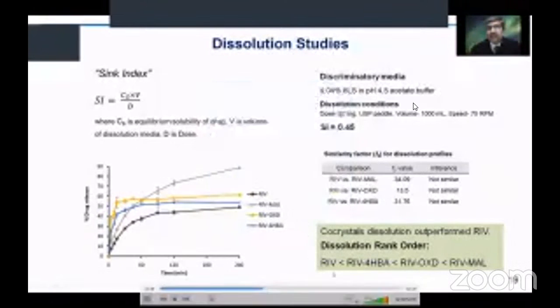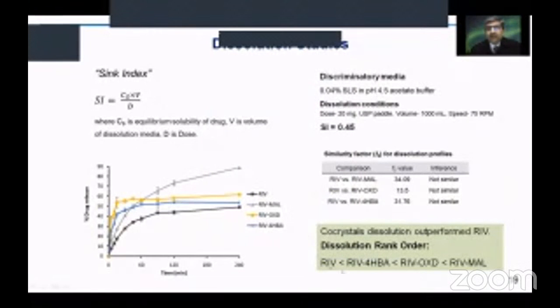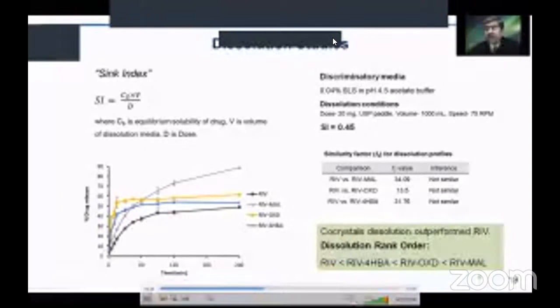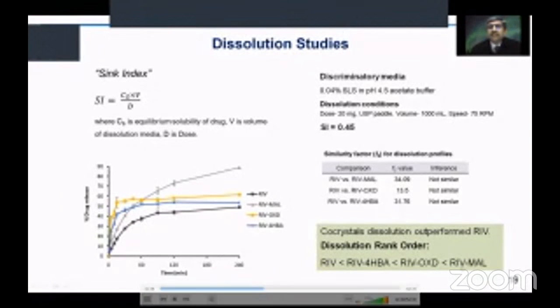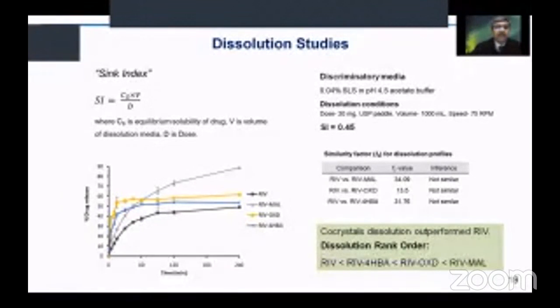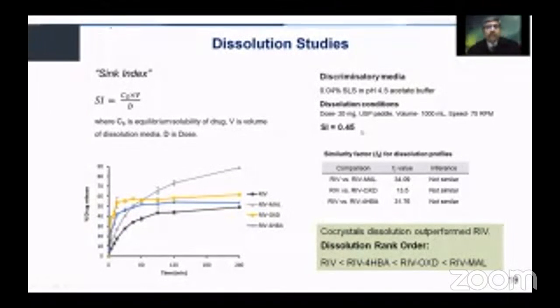The dissolution studies were carried out, and in this also the rank ordering was that rivaroxaban had the least dissolution rate, while the malonic acid co-crystal has the highest dissolution rate. The studies were carried out using a dissolution medium which had a sink index of 0.45, so that we were able to discriminate the dissolution profile from the various co-crystal candidates.